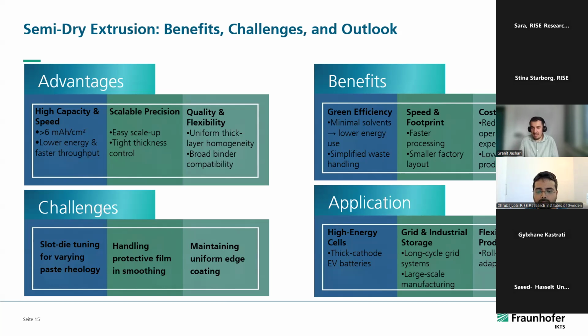Application, as I said, could be in really high energy cells, so thick cathodes for EVs, and also storage. Another advantage compared with the completely dry technology is that there we need a lot of adaptation that cannot be taken from the current processes the industry is using, because it's a rather different process. But in this case, we could still use the drying channels and the roll-to-roll system, and just adapt the step before the drying, using not batch mixing as in tape casting, but an extrusion process with a slot die, and then make a direct coating, and use the other parts that are already installed in the industry.